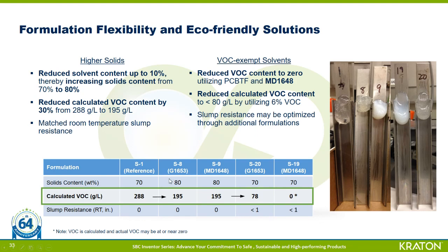This brought the formulation viscosity too low, however, and the sample ran down the vertical channel, creating a significant slump value. Therefore, we reformulated to increase the total solids content by 10%. This put us at 80% solids, as can be seen in sample S-8, to boost the viscosity back up, and then we again improved the slump resistance back to the similar test results that we received for the reference sample.